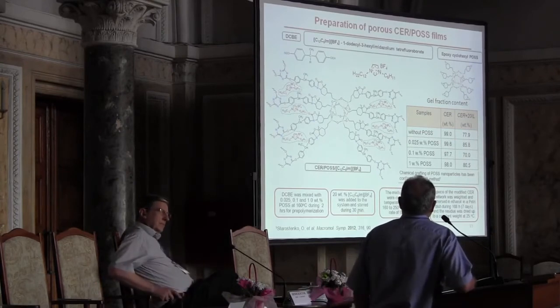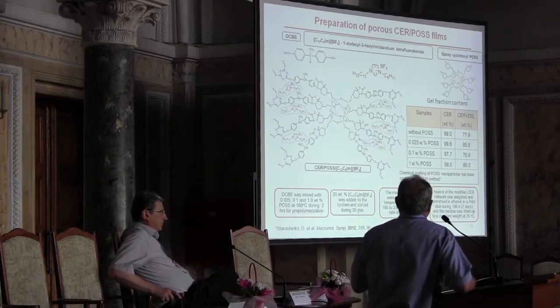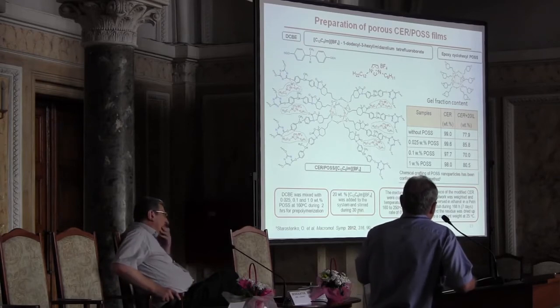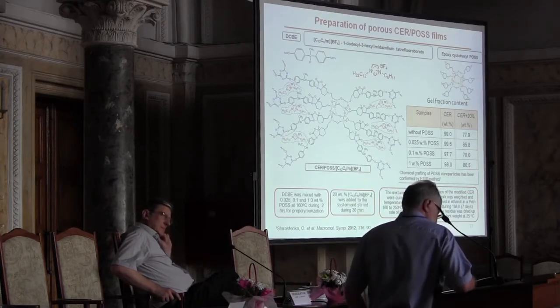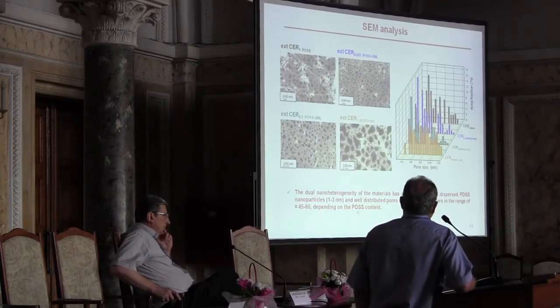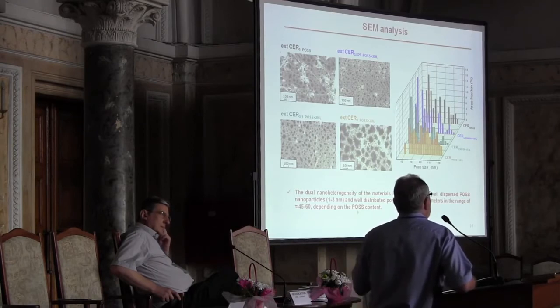We used the same polymer network and another ionic liquid, and also epoxy cyclohexyl POSS. After the synthesis, we got a hybrid organic-inorganic network which contains organic junctions and inorganic junctions in the polymer network, with high gel fraction content. Also, the micrographs show us a good, well-defined nanoporous structure. And we can also speak about dual nanoheterogeneity, because we have small nanoparticles